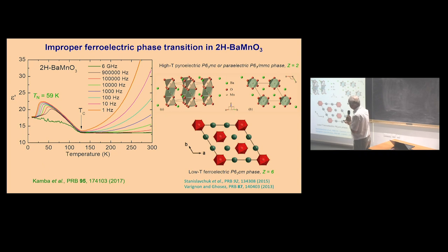But here it's not a relaxor ferroelectric. You can imagine that if you have a ferroelectric phase, the domains vibrate due to temperature, and these domains freeze out on cooling, and this freezing is strongly frequency dependent. Therefore, you have such a decrease of permittivity.